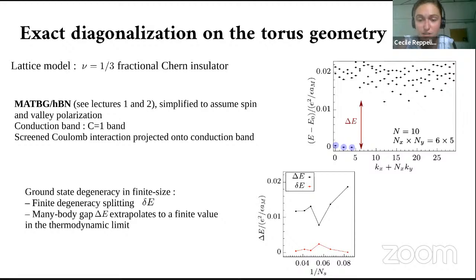Here, 1/ns is 1 over the number of moire unit cells, and in red is the splitting of this degeneracy. In finite size, there's no reason why the degeneracy should be exact - it's only exact at the thermodynamic limit. Because the sizes are a bit small, within this visualization it's hard to see that it goes exponentially to zero, so we're just happy enough to see that it remains small and much smaller than the many-body gap.